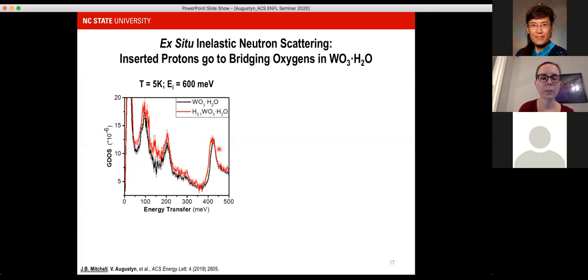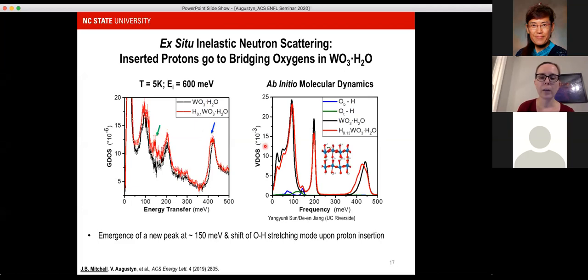The pristine material before electrochemical proton insertion is in black. In red, the primary difference after proton insertion are in these two regions here. So a new peak and then a shift of this mode that we assigned to the OH stretching. And our collaborators at UC Riverside did ab initio molecular dynamics, and they found that these exact features that we see are due to the presence of a proton at these bridging oxygen sites that are actually located within the layers of the tungsten octahedra and not in the water networks.